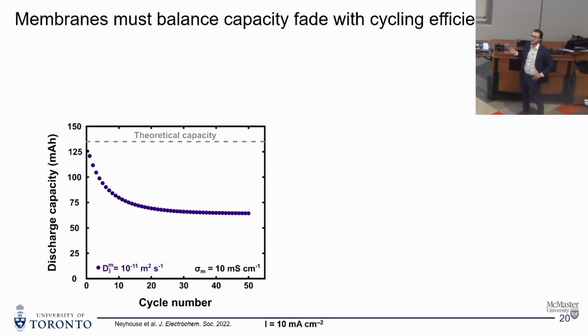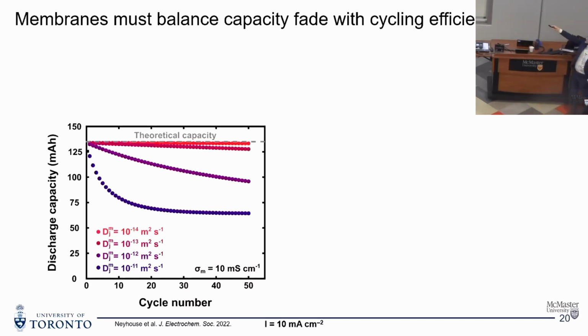So what happens when we're incorporating crossover here, we start from near some initial theoretical capacity based on the concentration and volume of our electrolytes. And as crossover proceeds, both electrolytes effectively become fully mixed, where we lower the diffusion driving force until we have essentially the exact same electrolyte on each side. And that plateaus around half of the theoretical capacity, as we're going to lose half of our species when you imagine mixing both electrolytes. So as we slow our diffusion down, we slow down that crossover. This is characterized by our diffusion coefficient, where we're going lower by orders of magnitude. We can see this capacity fade stabilizes. So if we get this crossover rate to be slow enough, then we can get pretty stable cycling over time.